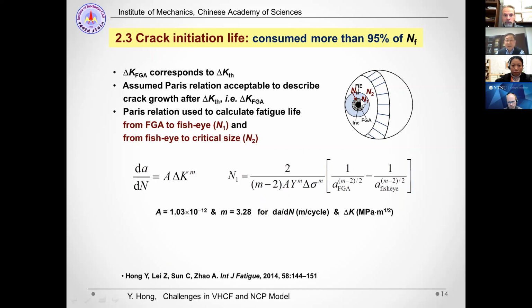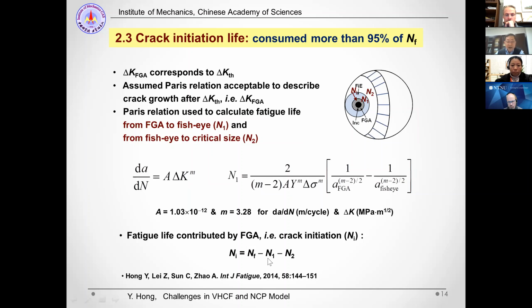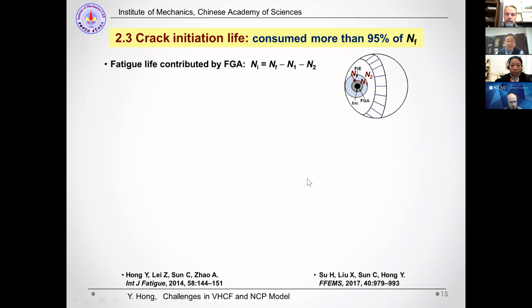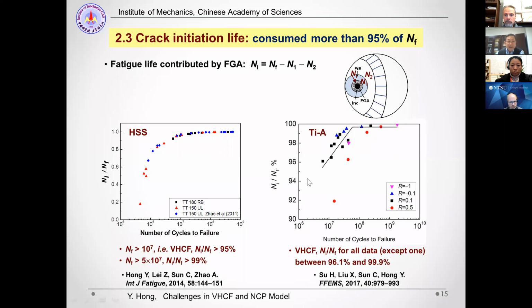Like here, from the boundary of FGA to the boundary of fisheye, that's N sub 1, and then from the boundary of fisheye to the final fracture point, that's N sub 2. For example, N sub 1 can be written like this, and we also can use such parameters for calculation. After this, we can obtain the initiation life by the total fatigue life minus N sub 1 and N sub 2. Therefore, we are able to obtain the result for high strength steel.